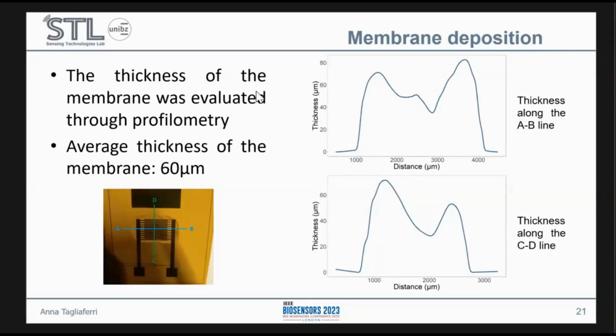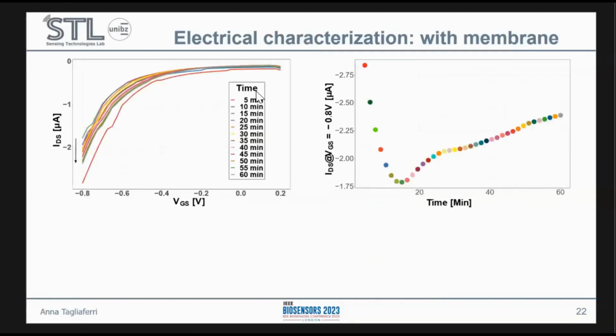We found that the average thickness of the membrane was around 60 micrometers, with some peaks at 80 micrometers. This technique suffers from the coffee ring effect, which we are hoping to mitigate in the future by not drop casting, but blade coating this membrane on the devices. After the successful deposition of the membrane, we still performed the electrical characterization, collecting 40 transfer curves over time,